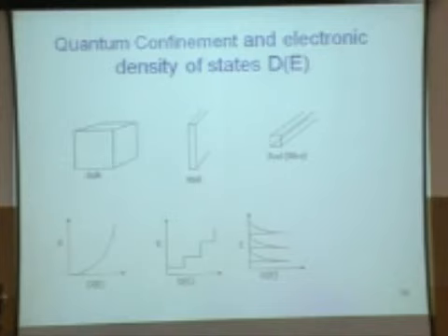So you can see here is a very interesting, simple case. Suppose my Fermi energy was somewhere here, the density of states is almost flat. So when I excite electrons thermally, I create holes and electrons. Because this is so flat, I'll have roughly the same number of electrons and holes. So that's the reason why a metal in 3D is not very good. On the other hand, imagine in this system, if I put the Fermi energy here, because there's an enormous difference in the density of states above and below, I will have a different number of electrons and holes. So that's essentially the physics, which tells you why going from here to here, I'll have some changes in the property.